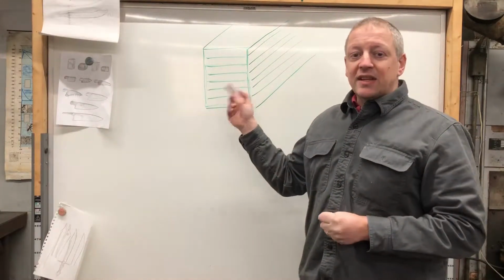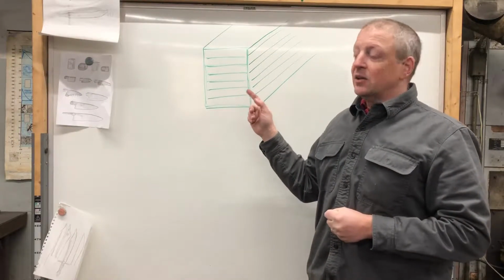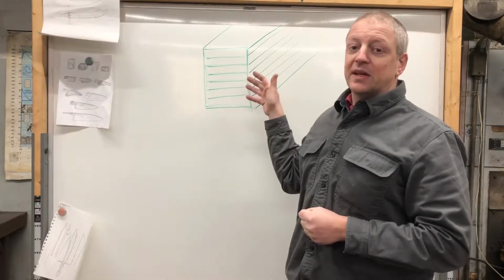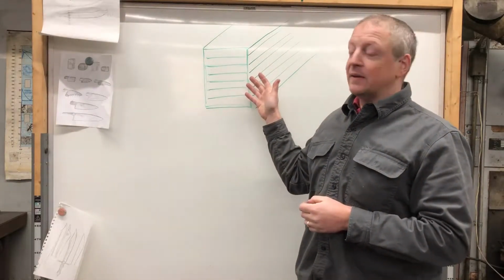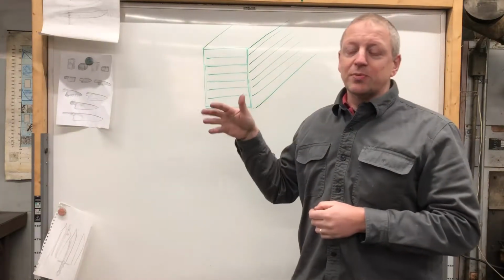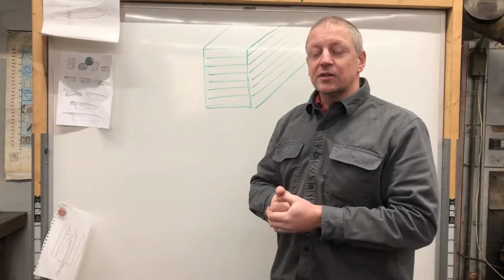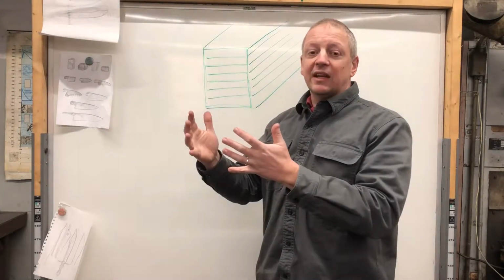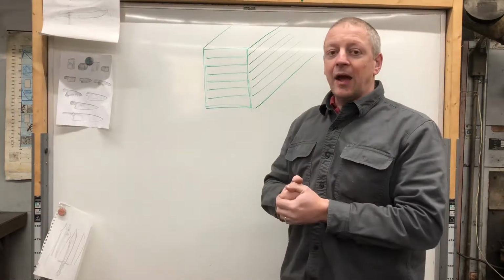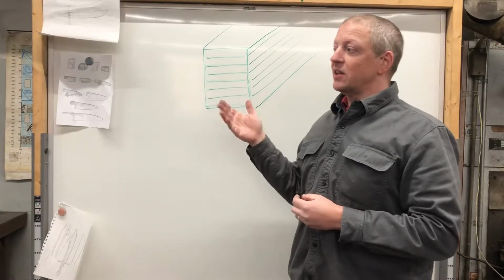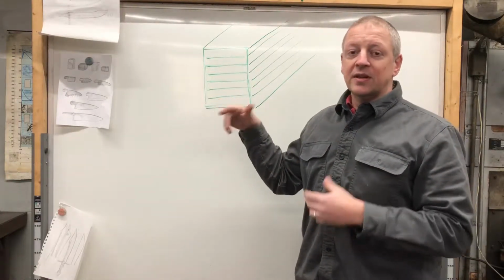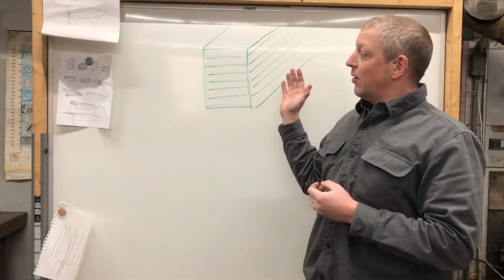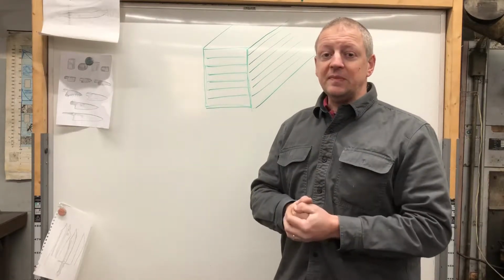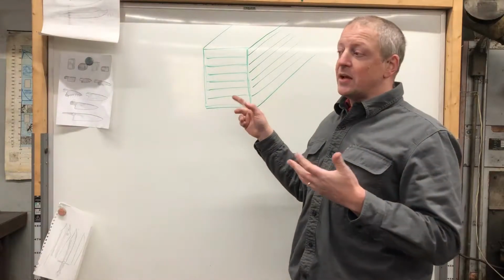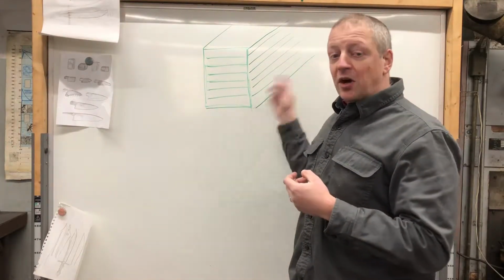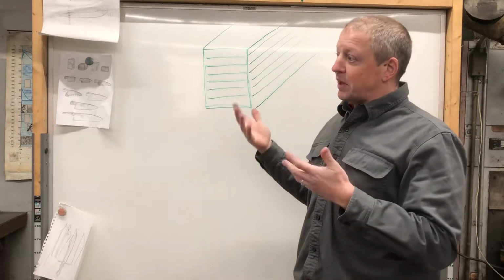So, going back to this, if you do flux the surface of your billet, really what you're aiming to do is not get the flux in between. If anything, you want to make sure the flux doesn't get in between. But instead, it's a coating. It's much more like what the Japanese would do with their clay coatings. Those clay coatings create an encapsulated atmosphere and help the steel clean itself. The steel is always fighting against the forge atmosphere, so if you can set up a situation where it's easier for the steel to clean itself, that's great. You'll get better welds. Lots of people do the same thing. They will weld all their seams, not entirely necessary, but effective.